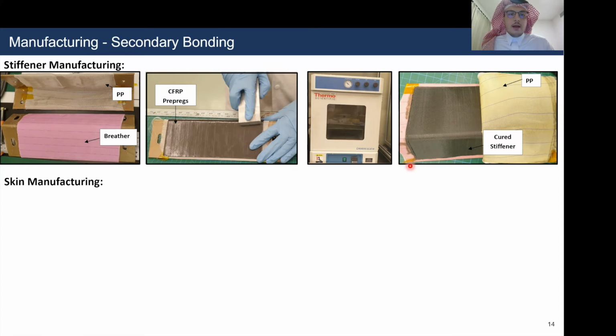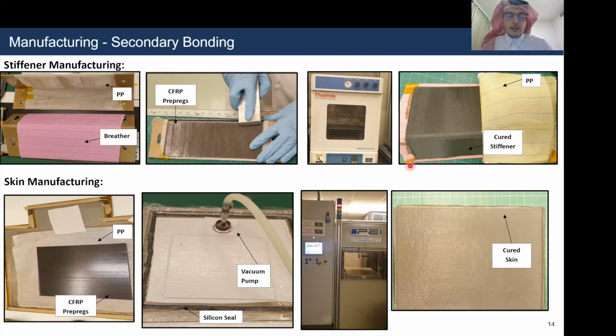So for the skin, the manufacturing technique was different, and followed a hot press method, where a metal mold was covered with a Teflon sheet, and then this Teflon sheet was covered again with a peel-ply fabric. And the CFRP prepregs were laid up. This time, 16 layers of the prepregs were laid up with the same respective quasi-isotropic stacking sequence, and then they were covered with the breather sheet, and then a silicon seal and vacuum bag was put on top of everything.